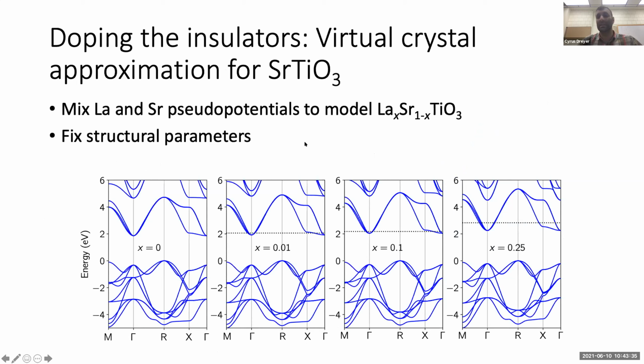So in strontium titanate, we test a slightly more sophisticated way of doping the material. We actually use the virtual crystal approximation to include some lanthanum character on the A site of strontium titanate. And we can show that doing this procedure basically shifts the Fermi level into the band gap. And we can compare that to our rigid band approximation.